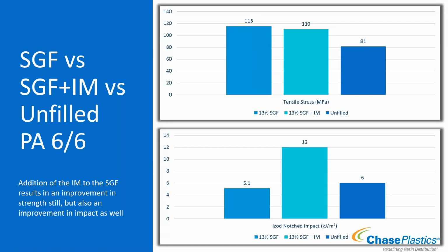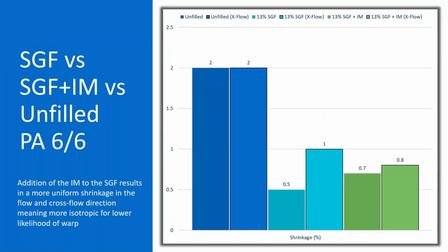And so we're able to achieve higher stiffness, strength, higher impact, and not have as poor loss of anisotropic shrink. If you look at unfilled, it's 2%. Then the glass filled, 0.5 and 1, it's half. Then glass filled and impact modified, you're at 0.7 and 0.8. The impact modifiers, those little pieces of rubber, disrupt the flow of the glass so it can't line up as easily, so they end up in different directions. This helps allow for more uniform, isotropic shrink. So you achieve better stiffness and strength, better impact, and more isotropic shrinkage.